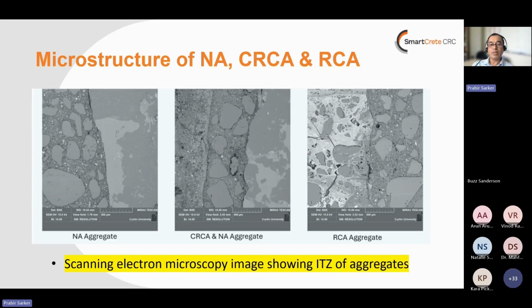Looking at the microstructure for natural aggregate, CRCA and RCA, recycled C&D waste aggregate, just to see the interfacial transition zone, we know that that is the weakest point of concrete. The well-known difference is that for concrete using natural aggregate we have one interfacial transition zone, whereas for any recycled aggregate we can expect there are two ITZs. One is the old ITZ and one is a new ITZ. So it is similar for both CRCA and RCA.